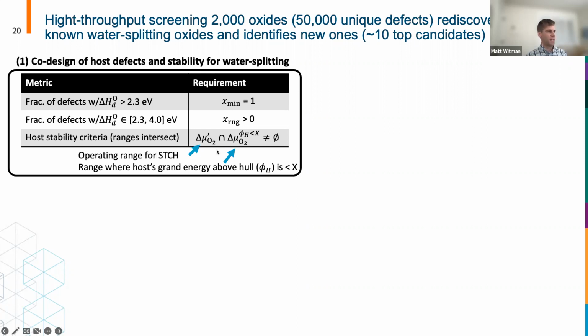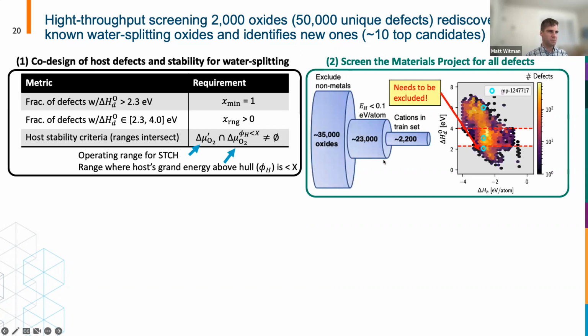So our material, of course, has to be stable within that chemical potential range. So we have this additional stability criterion that says the material must be stable. The material's grand energy above the hull must be below some threshold and intersect with the target chemical potential range. So we can do this down selection and quickly screen all of these materials.